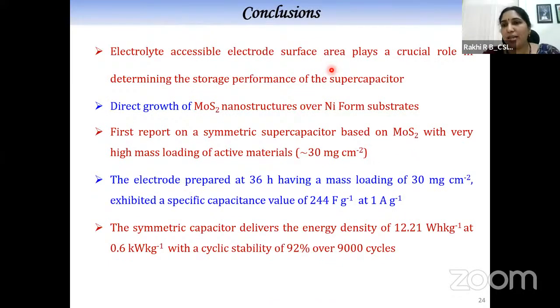I would like to conclude by saying that both the electrode morphology and electrolyte accessibility play a crucial role in determining the energy storage performance of the supercapacitor. In this particular study, direct growth of MoS2 nanostructures over nickel foam gives the maximum capacity performance. Otherwise, I can say that for any material, if you take a three-dimensional conductive collector and grow it directly, that is the best electrode for that particular material and for supercapacitor application. This is in fact the first report on an MoS2 symmetric supercapacitor with a commercial level mass loading, and it gave a specific capacitance of nearly 240 farad per gram at 1 ampere per gram with a mass loading of 30 milligram per electrode.